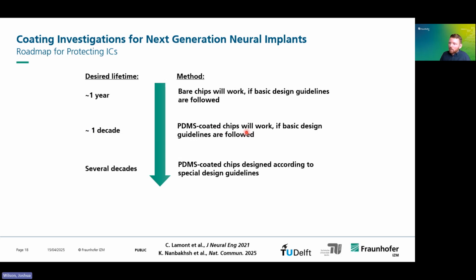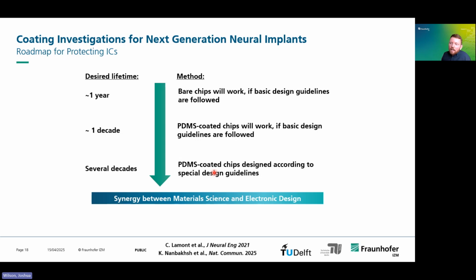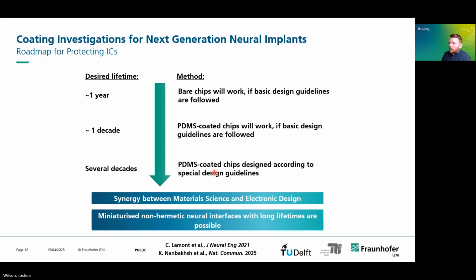But if you really want to push it into several decades, then you need to coat the device and also follow some special design rules like these shielding layers, and also using AC signals in the top layer. So what we see here really is a synergy between the materials science and the electronic design, and you need to think about both when you're doing your design. And also what we see is that miniaturized non-hermetic encapsulated neural interfaces can have long lifetimes.